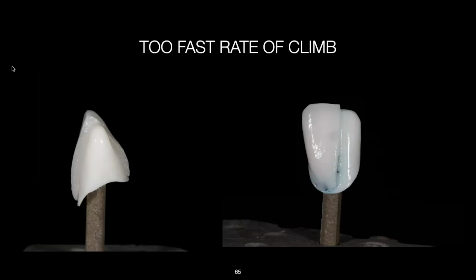And I do that to test to see if any of my veneering porcelain lifted off of the zirconia. So what happens is if you go too fast and you need to slightly air abrade the surface, you see how shiny that coping is from the bonding layer? That's because the bonding layer cooked twice. I cut that crown in half, but that was flat, okay? But still, if you dry it too quick and you fire it too quick, the ceramic will shrink and pull up on itself and it lifts off the margin. And the blue dye can tell you how bad it is.